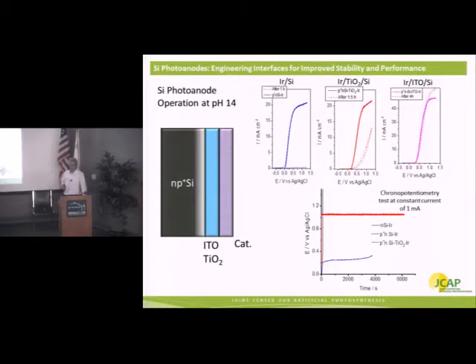You do require a bit of a higher potential to be applied in order to get the same performance. But after 4 hours of operation, it's performing exactly as well as it was when we first put it into solution. So we now have a silicon-based photoanode that can do water splitting. And impressively, this can be done also at pH 14. So for anyone that's worked with silicon, basic conditions, you will immediately oxidize or even etch the silicon depending on what you're using. Here we have a stable